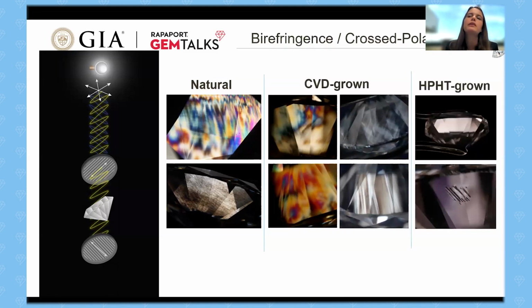But the reason I bring this up is that for the HPHT grown, because they are grown with very, very even pressures from all different directions, they actually have extremely low, unusually low strain and stress in them, which gives you this very clear view through the stone without any clear strain patterns, except directly adjacent to inclusions. So this in itself can actually be a very good warning sign that the stone needs to be looked at more carefully.